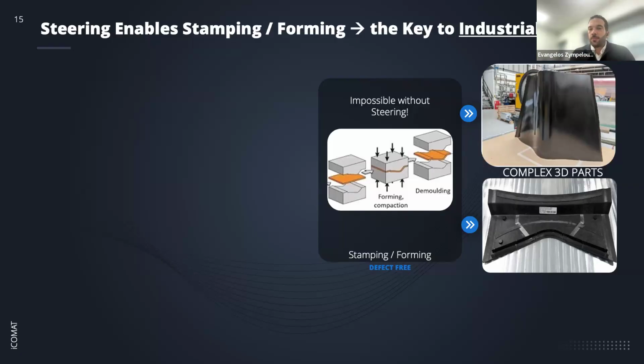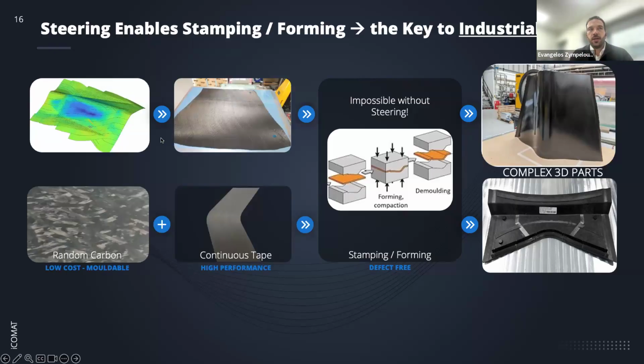And this works really well with metal because metals can stretch in all directions, but carbon fiber doesn't stretch. So if you try to form anything complex, like the fuselage of a fighter jet, it really is like taking a piece of paper and trying to wrap it around a football. It will create lots of wrinkles. So what we do is we use software, we predict where those wrinkles are, and then we pre-steer the fibers in 2D so that you can stamp form the component in 3D without any defects. So we can effectively engineer stretch into the 2D preform. And that allows you to produce many times faster.